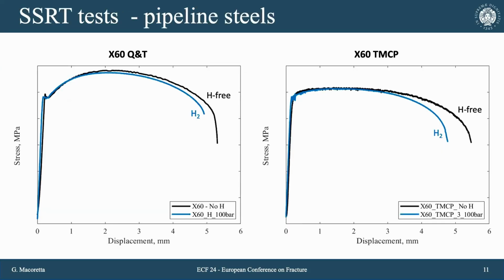If we go to see the results of the slow strain rate tensile test, here we see the typical curves of the effect of hydrogen, which we repeated at least 2 times for each test condition. I show here the typical curve that you observed, but the dispersion of the data, the scatter of the data, is very low. We can see that the effect of hydrogen for both materials affects only the plastic portion of the curve. The elastic part of the curve is not affected, and the effect becomes more evident after the necking phase. Until the necking, the material is not affected by the hydrogen present inside the hole.